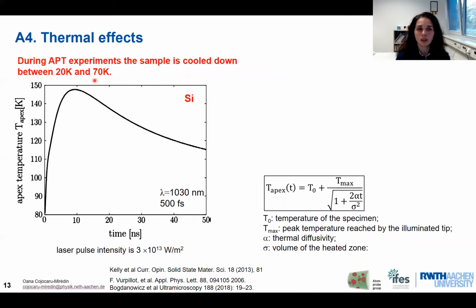And Kelly and co-workers measured the temperature at the apex of a tip, of a silicon tip, and they found out that the temperature cannot go beyond 150 Kelvin. And of course, the temperature at the apex of the tip is a sum of two contributions: the temperature of the specimen, and a ratio between the peak temperature reached by illuminating the atom probe tip with a laser, and a term which is given by the thermal diffusivity and the volume of the heated zone, sigma.